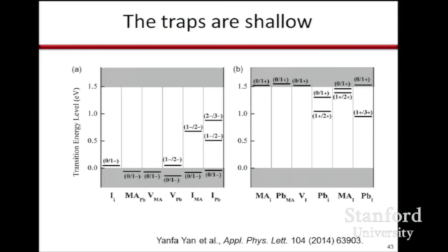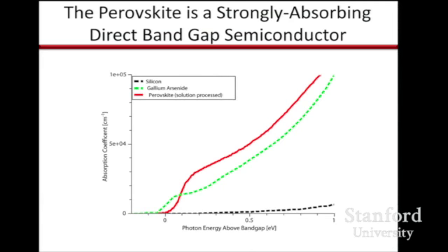States in the middle of the gap rapidly increase recombination, and they're real killers. Silicon and gallium arsenide have their traps there, and you're forced to use single crystals with those materials. But here, it's a very defect tolerant material, and that's probably why so many groups are getting high efficiencies so easily. It's also a great absorber. It absorbs light even better than gallium arsenide.